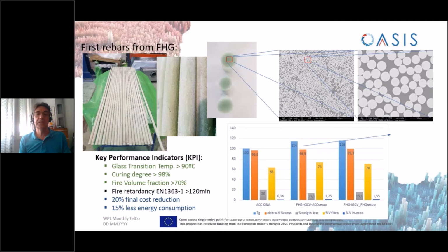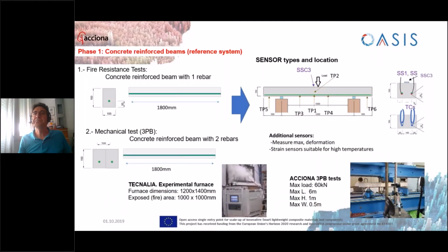we haven't reached the 20% final cost reduction yet, but we are close to this value. And also with the energy consumption, we have about 10% less energy consumption than using the traditional or the starting parameters. And regarding fire retardancy, we're still a little bit far from this value, but we are beginning the new testing of the second batch of rebars with up to 30% in weight of fire retardant nanoparticles during the next week. So hopefully we will reach this value in the next weeks.